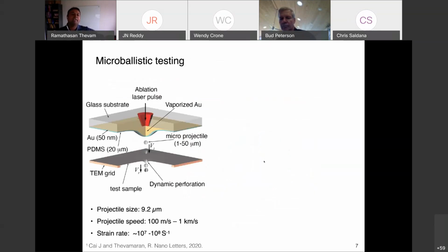What this microballistic testing system does is ballistic testing at a miniaturized scale, where your projectile is a microprojectile. You have a target material deposited on a transmission electron microscope grid, and you launch these microprojectiles selectively, one particle at a time, using lasers. To do that, you create a propulsion mechanism where, on a microscope glass slide, a thin layer of gold absorbs the laser energy and becomes gold vapor. That is trapped between the PDMS rubber and the glass, such that the rubber expands and launches the projectile.